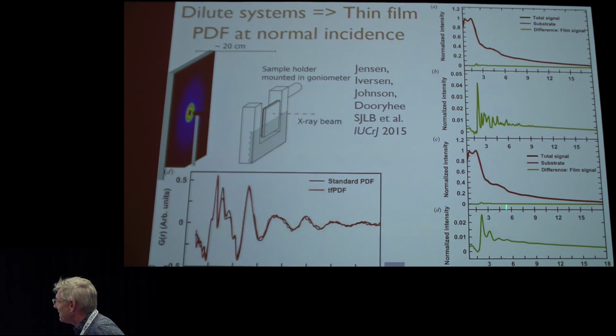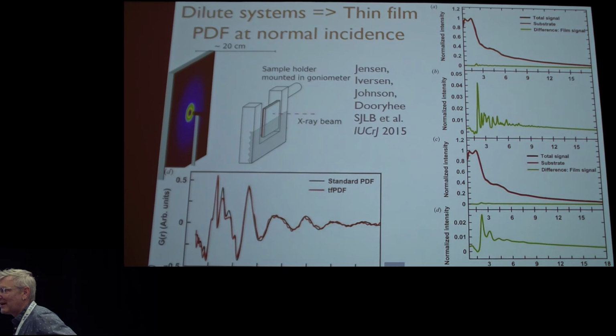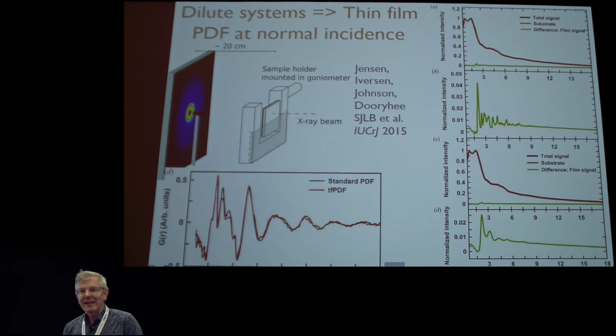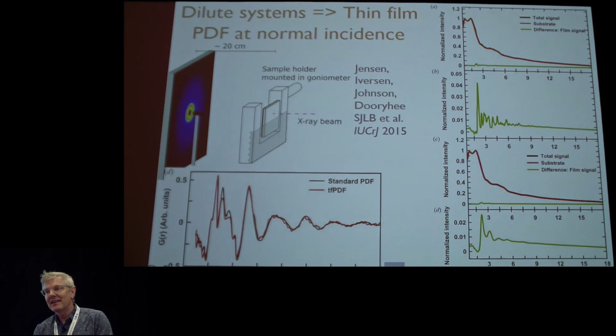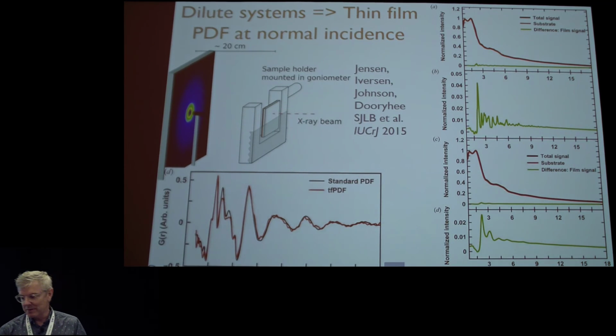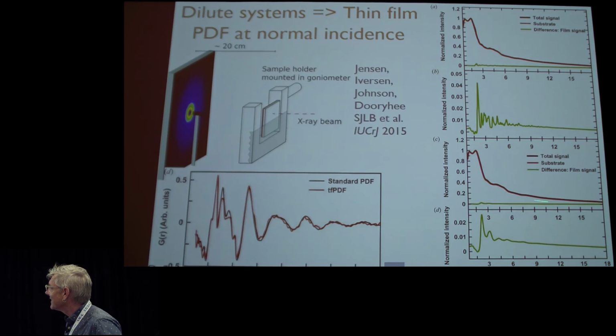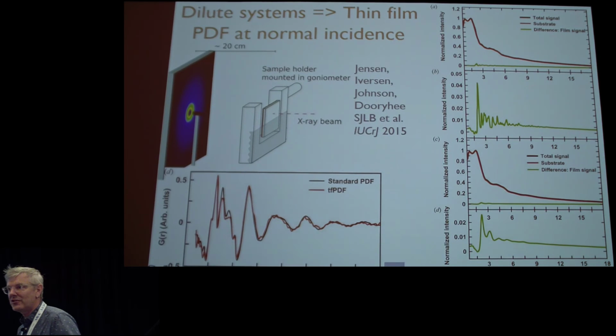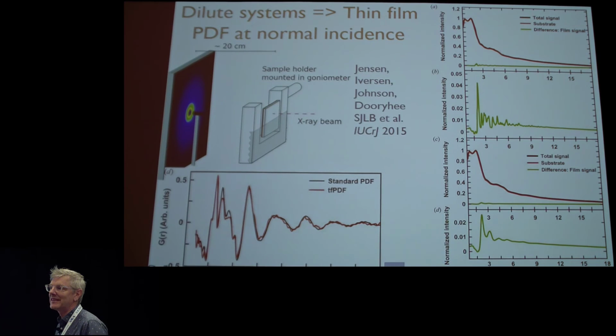And we verified that. This was an amorphous film on an amorphous substrate, blue and red. Green is the difference curve. This is the difference curve blown up. This is the G of r from the thin film in red. And this is from a standard PDF where we made the poor grad student make like 20 of these films and then scrape the thin film off into a powder and load the powder in a capillary for a conventional measurement. But you can see that we're really getting the right signal out from the thin film. So we can look at thin films. The smallest thin film we've been able to measure the signal from is less than 100 nanometers thick.